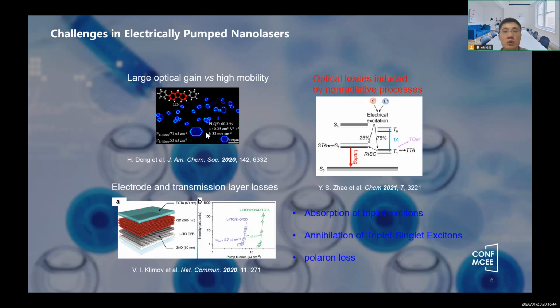The challenges mainly include the contradiction between large optical gain and high carrier mobility in gain materials. Generally, achieving high carrier mobility requires tightly packed molecular structures, but this tight packing can lead to fluorescence quenching. A balance between these two factors is necessary. Compared to optically pumped devices, the introduction of electrodes and transport layers in electrically pumped devices introduces additional losses, significantly increasing the laser threshold. Furthermore, the presence of non-radiative processes in the material greatly limits the realization of electrically pumped lasers.